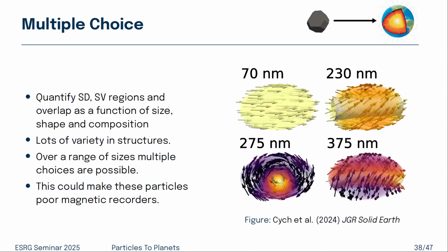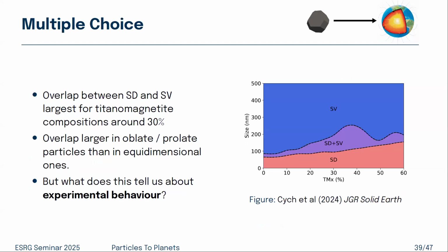So I did this over a range of shapes. You can see that you don't just get vortexes along the long axis, you get a load of weird stuff as well. In this study, I saw vortexes along the short axis, vortexes that are sort of bendy slightly towards various directions. And again, there's this kind of whole menagerie of behavior, right? Which again might indicate that you've got some potential problems in your experiments going on.